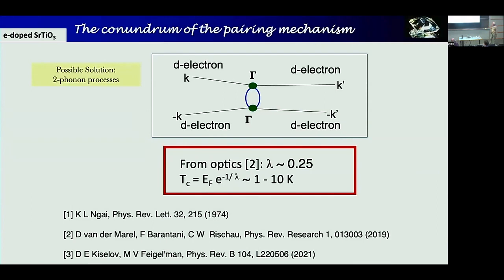So one thing that was not in the paper of Balatsky, but that actually may save the day for them, is to say, okay, maybe if you can't exchange one phonon, you can still exchange 2 phonons together. There is some sort of selection rule that would take you from an even band to an odd band if you emit a transverse optical phonon. But if you emit 2 of them, that doesn't happen. You stay inside the same band. And so the idea of Ngai from 1974 was that you also have these processes. They could be quite important in strontium titanate, but he didn't know the numbers at the time. And so he predicted that these 2 phonon processes could be the mechanism of pairing in strontium titanate.